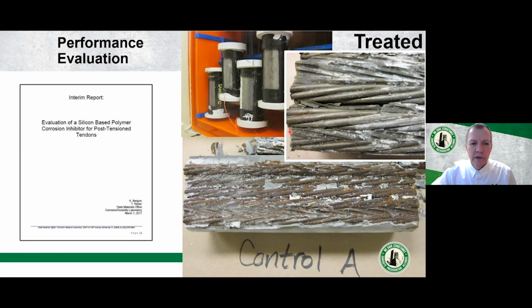And so there are very interesting and good photos in there showing not only quantitatively, but qualitatively, you can see there's a big difference in the amount of corrosion between the treated samples and the untreated or the control samples in this evaluation that they did.